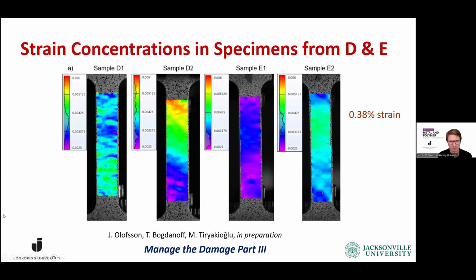Then we also took samples from these positions and again applied digital image correlation. The 2 samples that you see on your left side are from position D, which is the location that stood out as different. While the 2 on the right are from the area which is actually the best, which was just next to the really bad position. So you have really good properties. And you're looking now at the strain field when all of the samples are subjected to the same level of deformation, corresponding to around 0.4% of total strain. So we're around the yield point of the material.